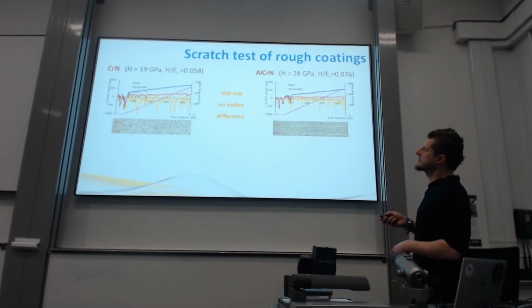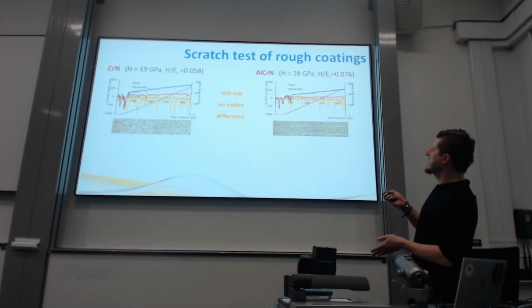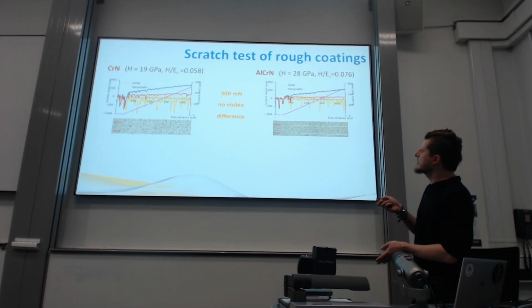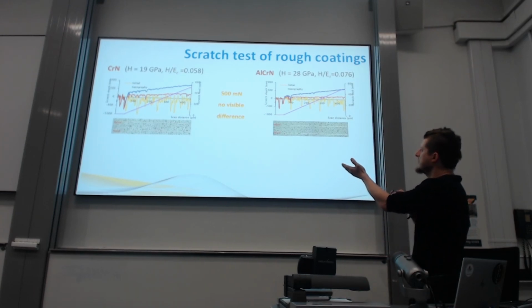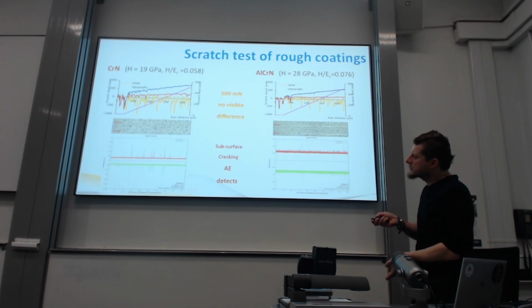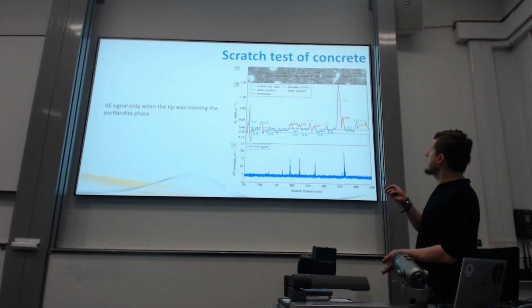And more cracks. Two quite rough scratch tests cannot be distinguished using visual observation and the depth change record, but acoustic emission gave some differences. There is more signal in chromium nitride than in the second sample. Some concrete, only one part of the concrete gave some acoustic emission, the others not.